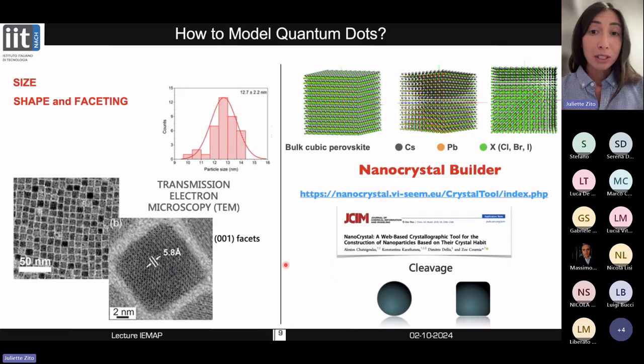And the very first step when you want to build a model is to look at the size, shape, and faceting. So for instance, if we take the case of this perovskite material made of cesium, lead, and a halide, that can be chloride, bromide, or iodide, from experimental analysis, and in particular transmission electron microscopy, you know that in most of the cases, these perovskite quantum dots have a cubic shape, exposing these 001 facets here. And you can also get some information about the size of the particle and the size distribution.